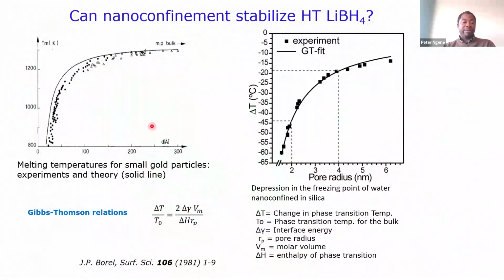This is also shown, for example, in the melting temperature of small gold nanoparticles. If you make gold very small, you can achieve a significant decrease in the melting temperature just by decreasing the size. The same thing here, the depression in the freezing point of water. If you confine water in silica, you can see that the freezing point will change to a large extent depending on the radius of the pore that you put your ice in. It all has to do with the radius here. It also has to do with the interface energy between your material and where you confine it.